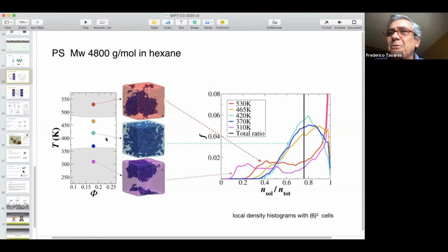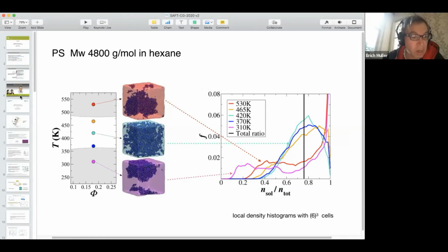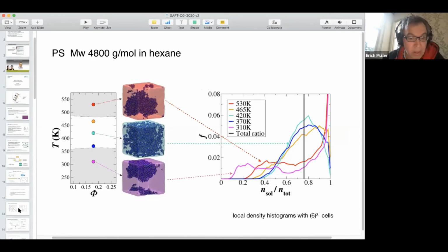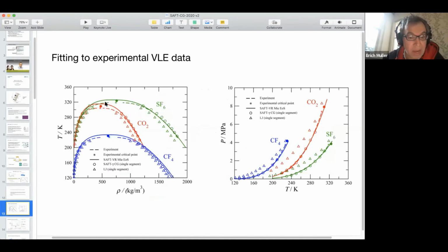So if you look at some of the results that we show, let me see if I can share the screen in a second. That's why it captures the critical region very well. I always wonder the same. Yes. So you can see that the critical region is captured quite well, much better than what you would expect with a more traditional SAFT, which would probably overshoot in this region. Yes, so we spent a lot of effort getting this as right as possible.